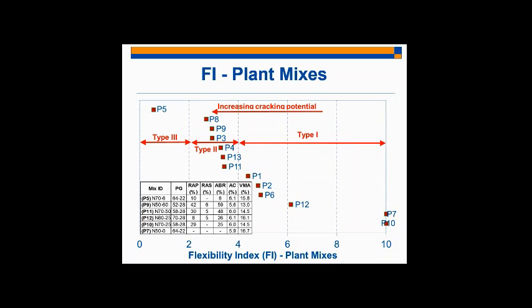If I look at, for example, P10, which is so well performing that it's actually off of the flexibility index chart, the value for that is past 10. We just put it right there for demonstration purposes, basically. But it's much higher than 10. It's flexibility index value. And P10 is basically a mixture with 25% ABR, a very soft 58-28 binder. Then as I move towards the left of the figure, I'm approaching mixtures which are not so good in terms of resisting low temperature cracking.